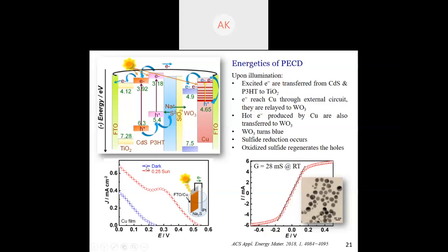For further checking it, we have run LSV with only FTO copper in Na2S solution with a platinum electrode. We see in dark, it's the blue line, and under 0.25 sunlight, you get a significant improvement. Now, had it been only SPR, then under illumination, there wouldn't have been any effect. So the curve would have retraced the dark curve. But when you see a certain amount of photocurrent under 0.25 sun, you can say it is a support to hot electrons. These copper films have nanoparticles of 10 to 25 nanometers. They show a conductance of around 28 milliSiemens at room temperature.